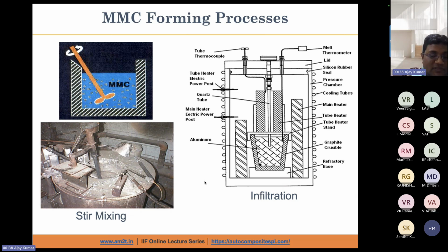One casting process that was introduced a long time back is stir mixing. So we can use the stir casting process, where we can mix the reinforcement particles in the metal matrix, where we can use the mechanical stirrer to mix the particles to avoid the agglomeration. We can also use ultrasonic vibration methods to avoid the agglomeration, so that these reinforcement particles can be mixed uniformly in the metal matrix.